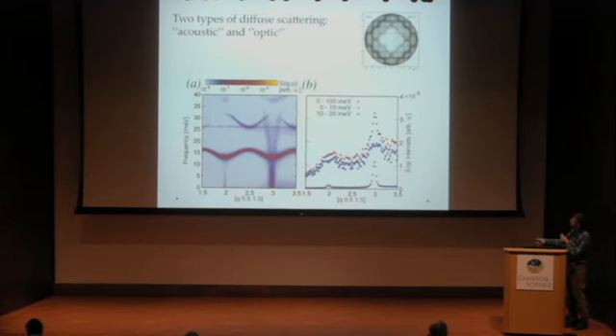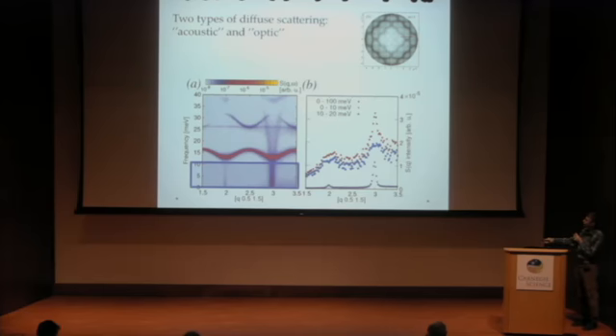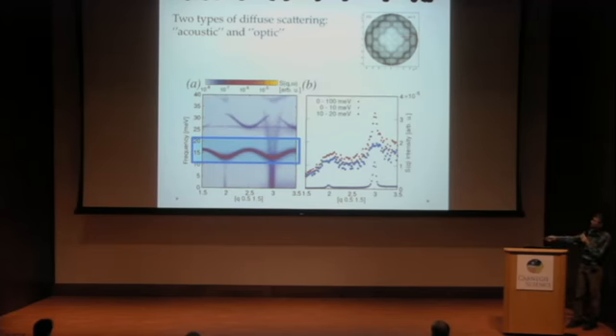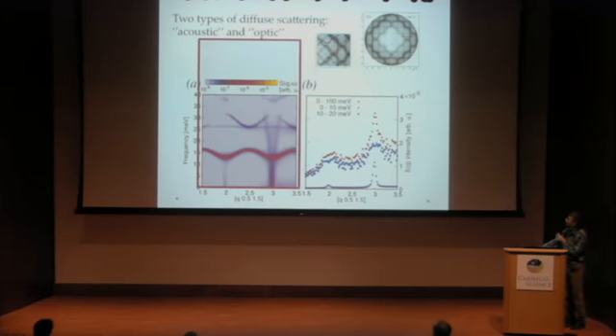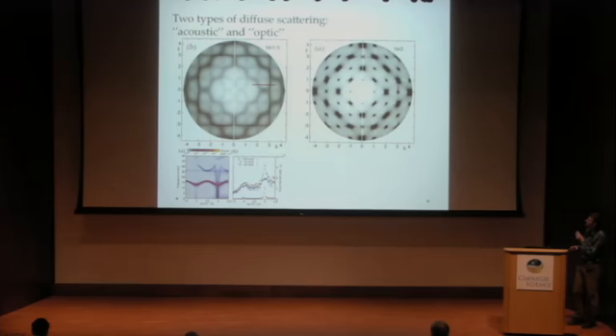We can do more. We can actually trace how the intensity integrates part by part. For example, if you integrate the intensity over the first 10 milli-electron volts only, then you would mostly get contributions from these pieces, and you see that it has peaks here and there, just at the position of the sharp lines. If, on the other hand, you integrate between 10 and 20 milli-electron volts, you would integrate mostly this wave, this acoustic branch, actually the zone boundary, and this would give something which is much broader, and it's related to this intensity. And you can integrate everything, as actually in the X-ray experiment. What we do in the usual diffuse scattering experiment, and then you have the red curve, which corresponds more or less to the intensity measured in the diffuse scattering experiments.